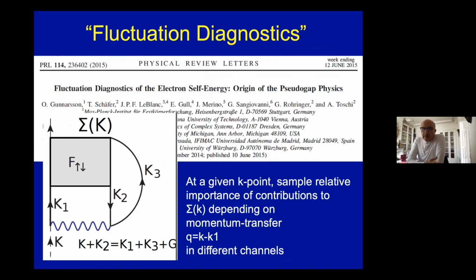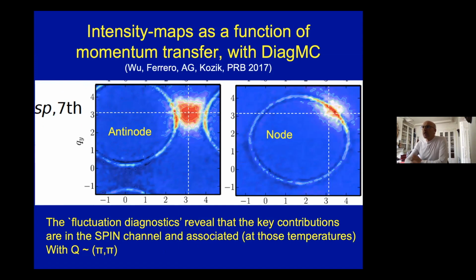So what is the physical origin of the pseudogap? Well, here we can resort to a beautiful set of tools that were pioneered by our chairman and by Ole Gunnarsson and co-workers, which is the so-called fluctuation diagnostics, which I don't really have time to describe in detail, but which is basically a way to do a surgery of the self-energy and understand what are the fluctuations that dominate the self-energy. And of course, this was first done with DCA with a certain momentum resolution. The diagrammatic Monte Carlo allows us to do that with very, very good k resolution.